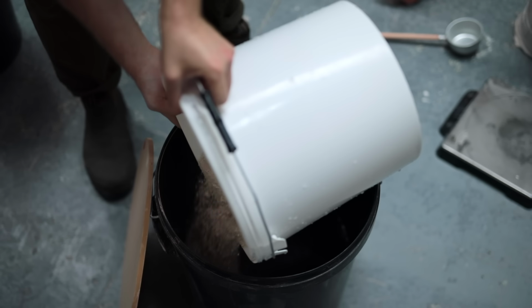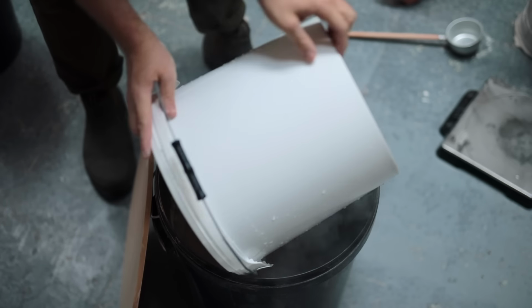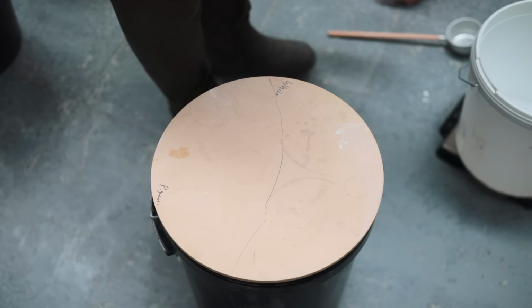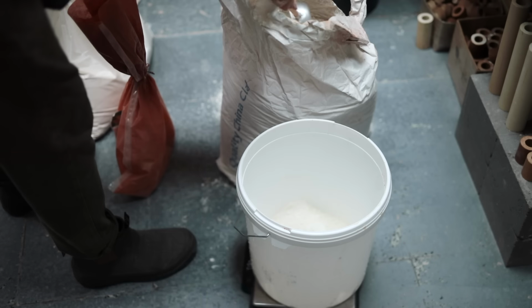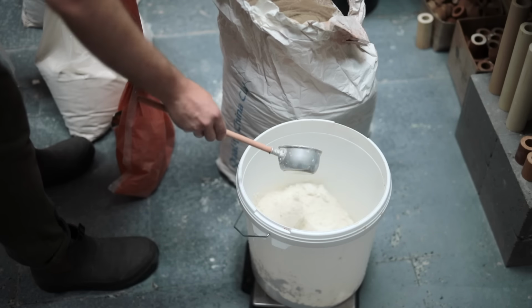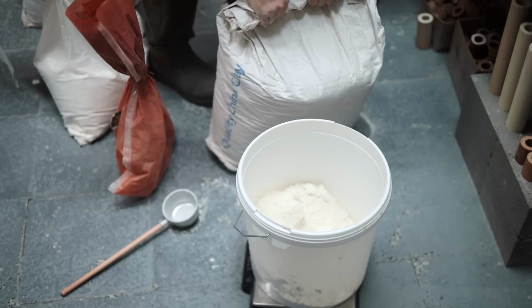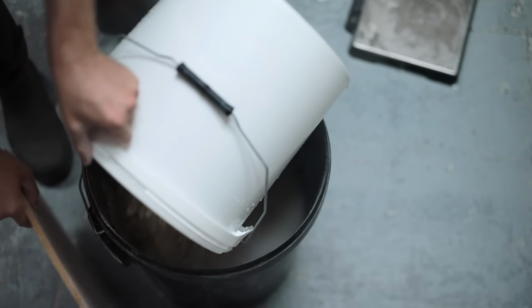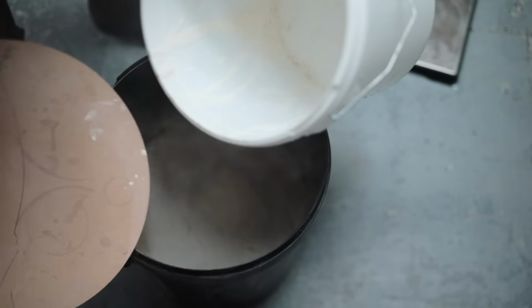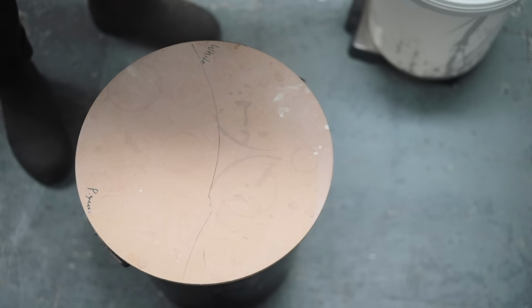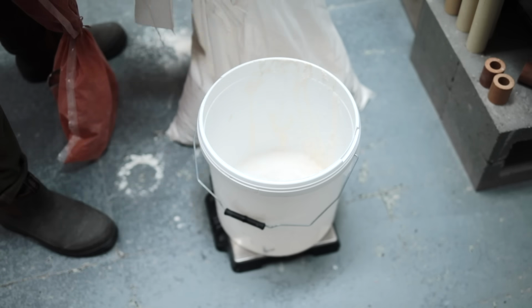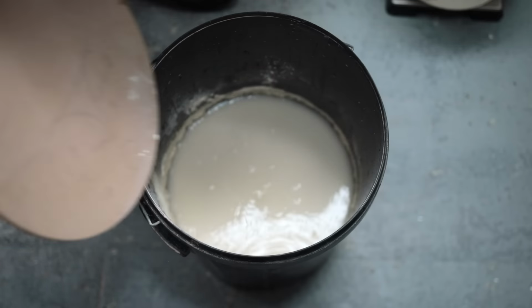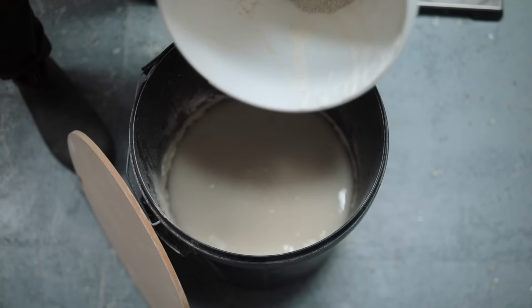I'm starting with potash feldspar, which I dump into the water, and then I slide a wooden bat over the top to stop any more dust from escaping. This will be the glass former of the glaze. Next is china clay, or kaolin. This is a stiffener, and it should help stabilise the glaze, so it doesn't melt and move too much. Next comes a bit of dolomite, which will help create a silky, smooth surface to the glaze that's slightly matte.